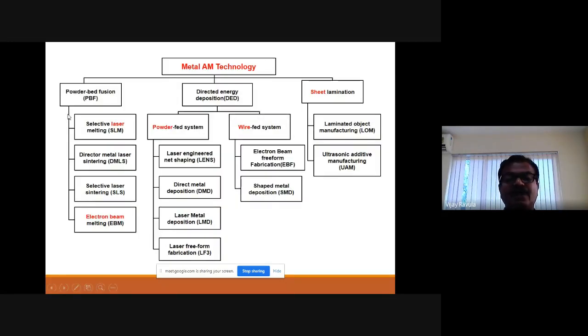So how do we do that? You can do powder bed fusion. You have a powder bed, and the powder is melted layer by layer, as per the 3D model, which is all sectioned, and the powder is melted by the laser. So you can have selective laser melting or direct metal laser sintering. In selective laser melting, you have a powder bed where the powder is filled as a layer. Then the laser moves as per the contours given in the drawing, and they melt and get welded to the layer below. The other, direct metal laser sintering, has a nozzle in the powder hopper that moves along the contours as per the drawing, and the laser moves behind it and melts the particles so that they get welded to the layer.